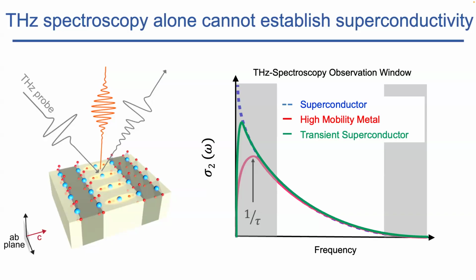So that's the reason why this is necessary but not sufficient. The way you should solve this problem is you do the following. Usually, if you take a material, you cool it down and then turn on a magnetic field, you have the same problem that you have here. If you turn on the magnetic field after you've cooled this down, what you will measure is the 1 over omega response. You look at magnetic field exclusion.